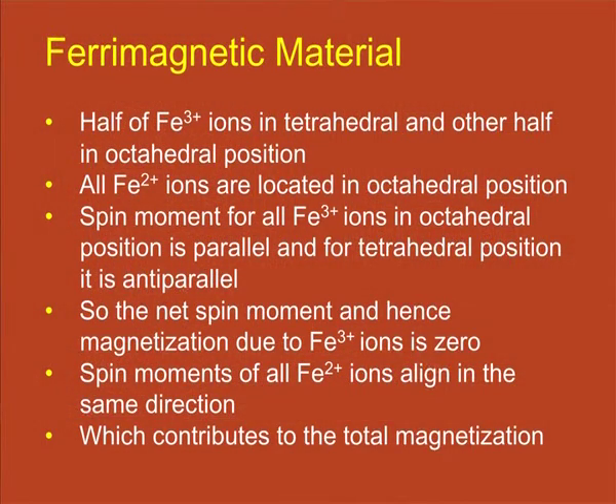Now, if we present the behavior or the nature of magnetic moment in this material due to Fe+3 and Fe+2 ions, because we have isolated them in terms of their position in the lattice, the Fe+3 ions present in the octahedral position, let us say, are in the up spin direction, then the Fe+3 ions present in the tetrahedral position will be aligned in the down direction.